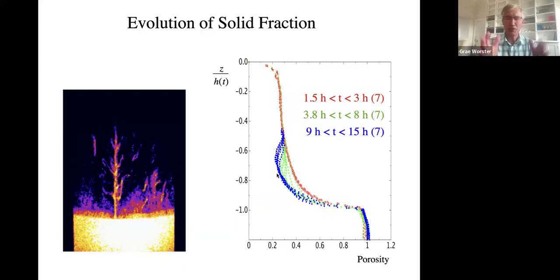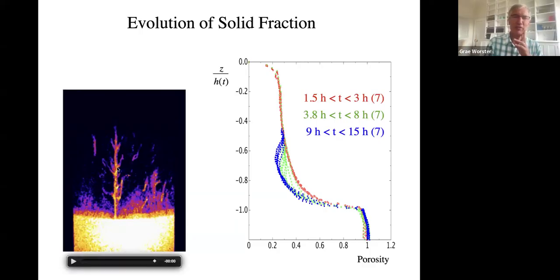And because the space is reducing, the resistance to flow is increasing. The Rayleigh number is decreasing. So there's a competition here. The Rayleigh number exceeds a certain value which allows convection to happen. Convection causes these brine channels to form, which takes the brine out of the sea ice into the ocean. In consequence, more ocean water has to come in to replace that brine, and that leads to more freezing and a reduction in the porosity, a reduction in the amount of water left behind.